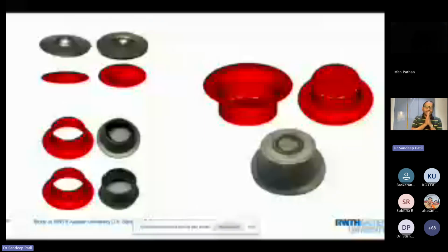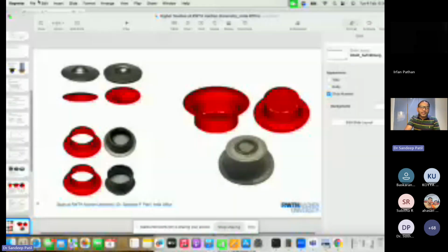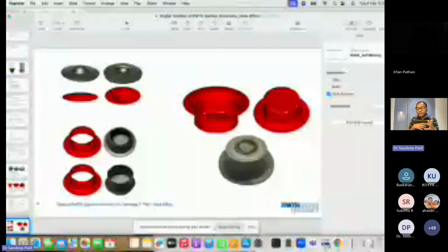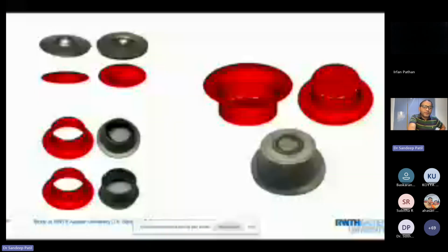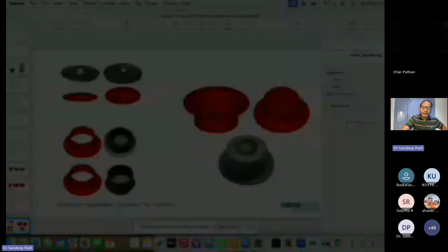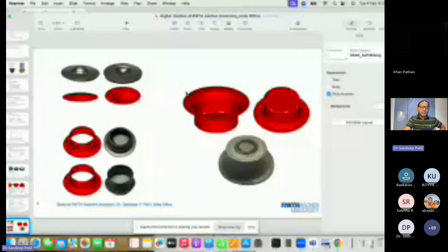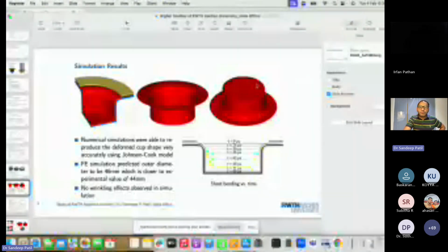Also we studied the damage. If you look at the first figure, it was for the low loading. So let's say detonation did not happen correctly, the diaphragm was ruptured abruptly, then we saw this kind of behavior, and we compared with the experimental values also. Then we carried out the medium load, which was perfect to form this kind of sample. It was perfect.